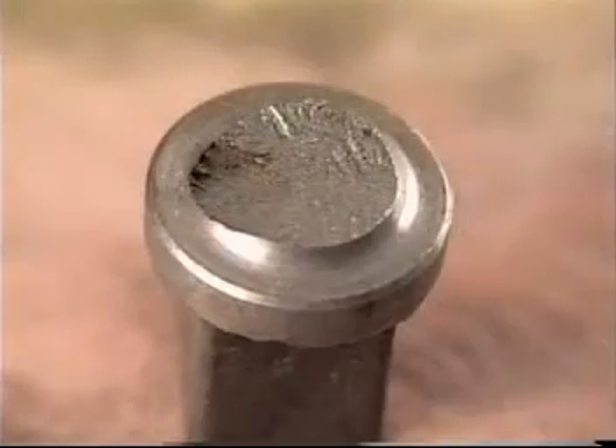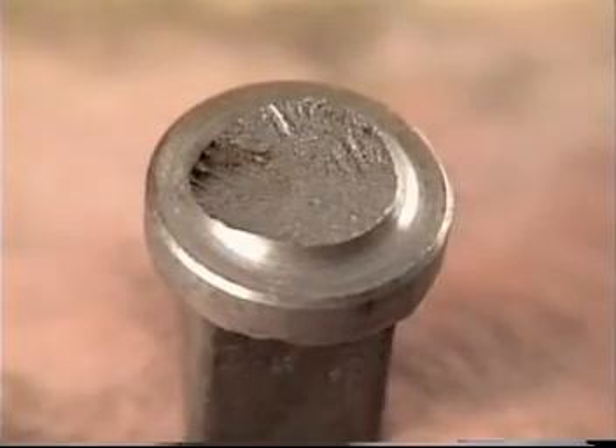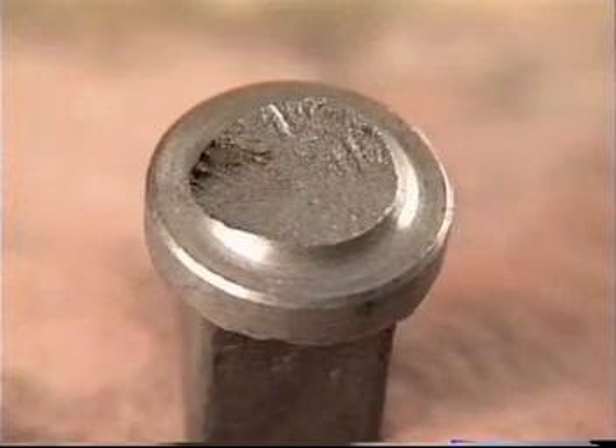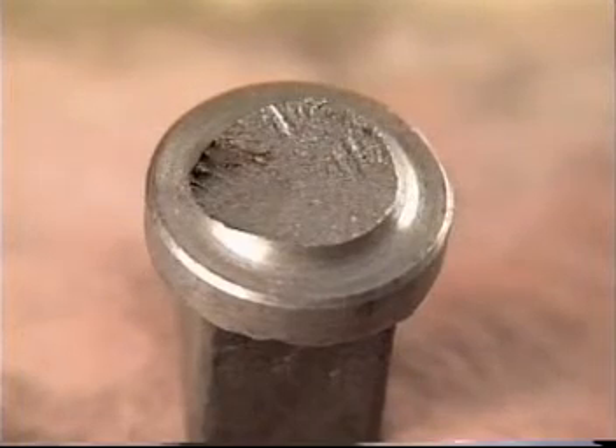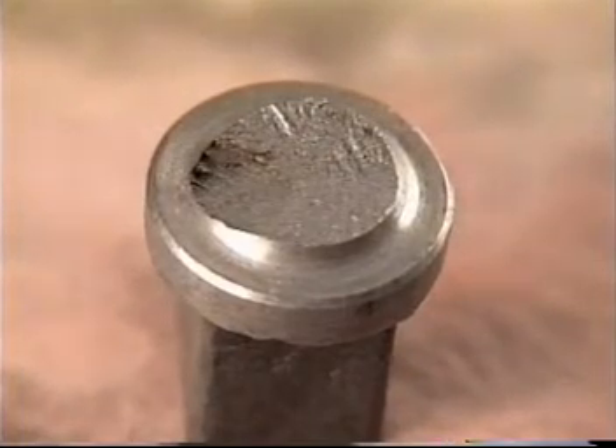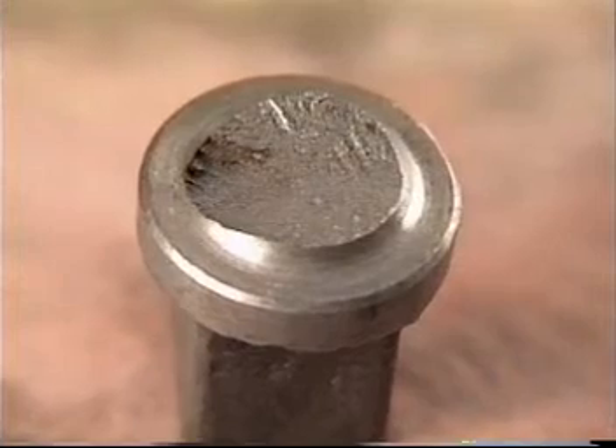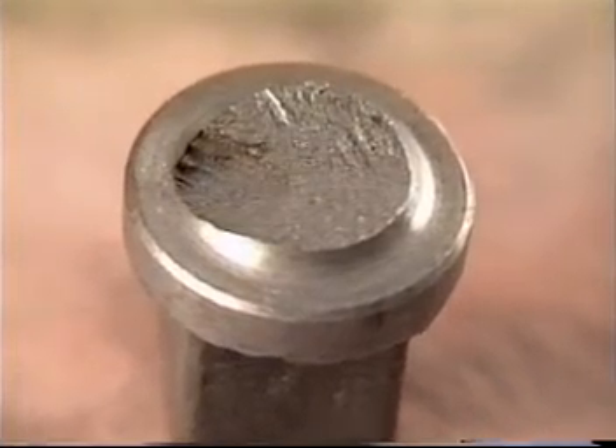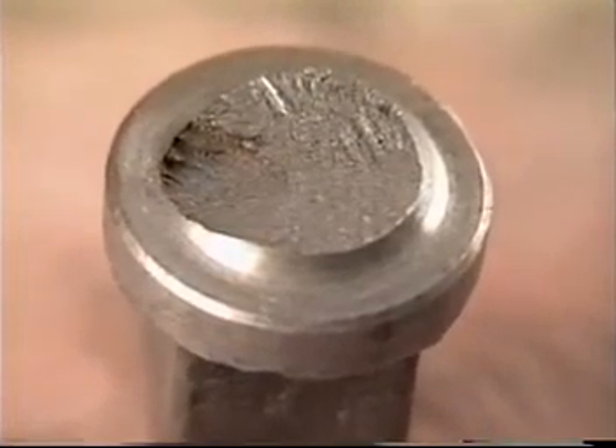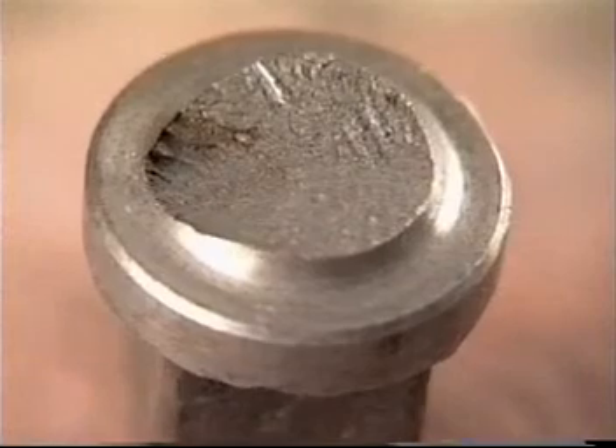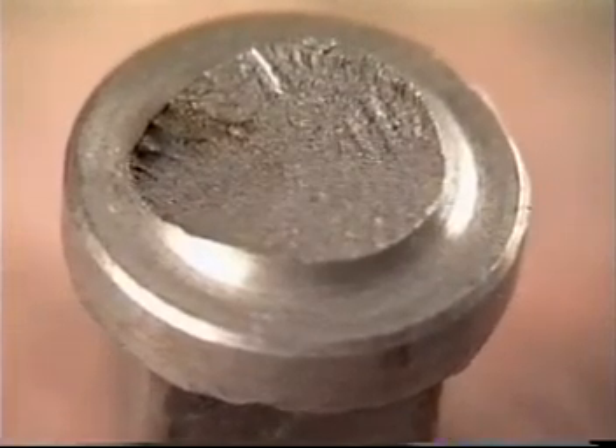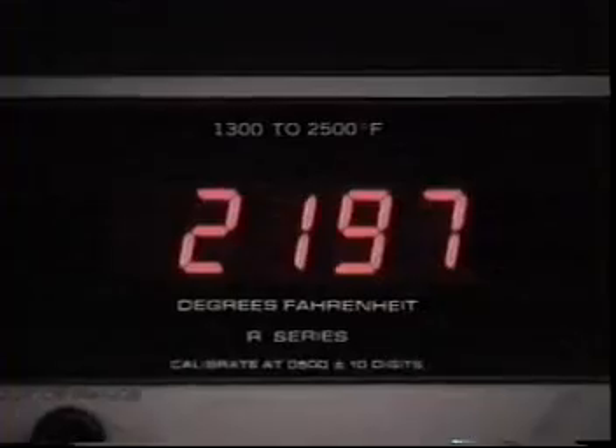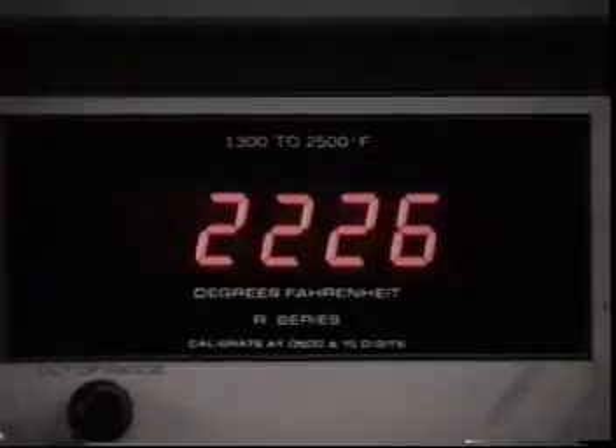This type of break is not H2S embrittlement. It is incipient grain boundary melting. This condition is caused by forging the rod at too high a temperature for the steel. Unfortunately, no inspection exists that will catch this before it is shipped. Fortunately, these pins will usually break off during the makeup procedure. Norris has virtually eliminated the incidence of incipient grain boundary melting by using optical pyrometers on our forging equipment.